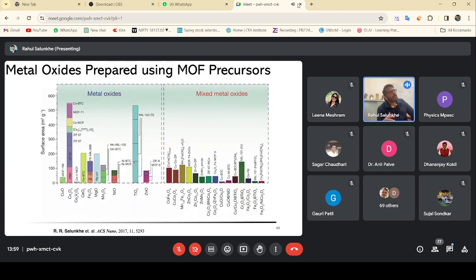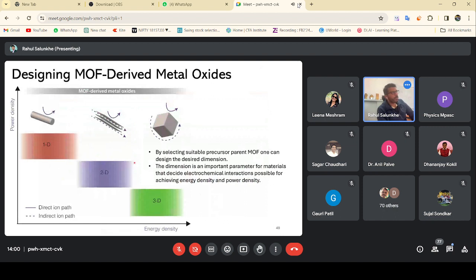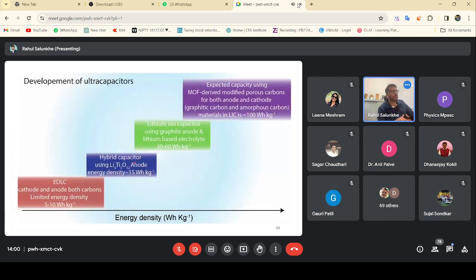So this method is not only limited to carbon materials, but various types of metal oxides can be prepared by this kind of method. Various metal oxides and mixed metal oxides can be prepared by this technique. So we can design different kinds of one-dimensional, two-dimensional, or three-dimensional material. By selecting a suitable precursor and parent MOF, one can design the desired material. The dimension is an important parameter of the material that can decide the electrochemical interaction possible for achieving the energy density and power density. So this is not only limited to the EDLC type.